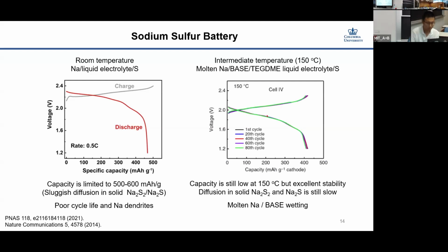And there are people who look at the so-called intermediate temperature sodium sulfur batteries, where you have a beta alumina solid electrolyte to separate the negative electrode and positive electrode. And in the positive electrode, we have ether electrolytes to help with the kinetics. But again, the kinetics of sodium disulfide and sodium sulfide is really bad, so you actually cannot utilize them. So the capacity is also limited to about 400 mAh/g. And also there's a wetting issue between the molten sodium and the alumina solid electrolyte.